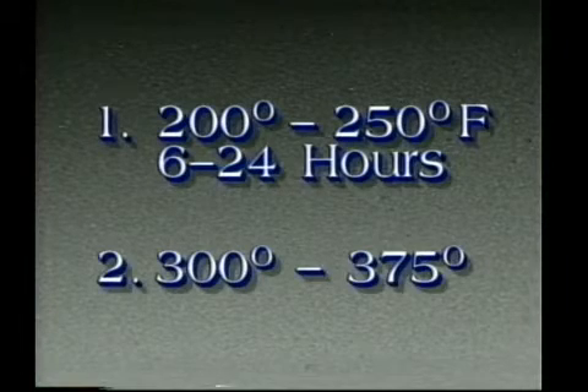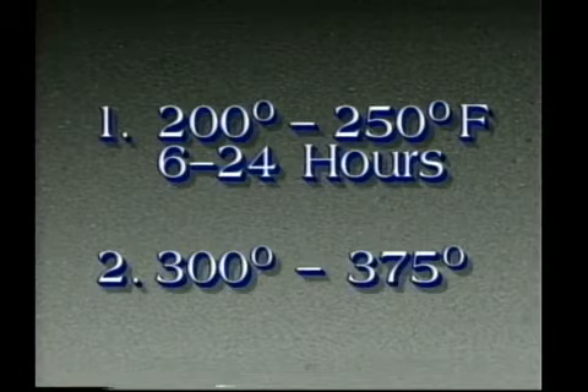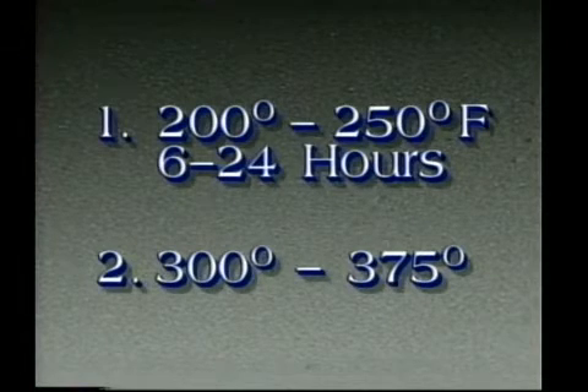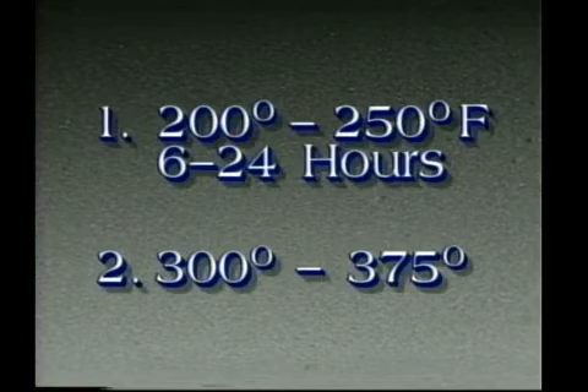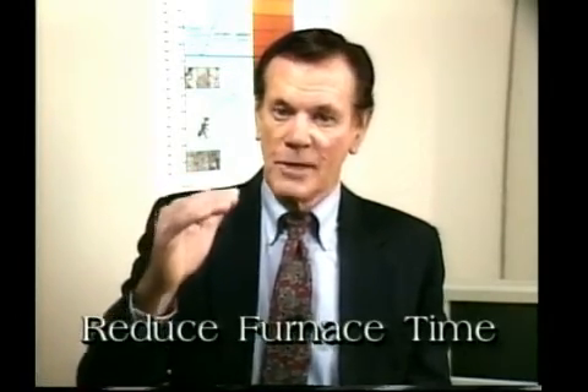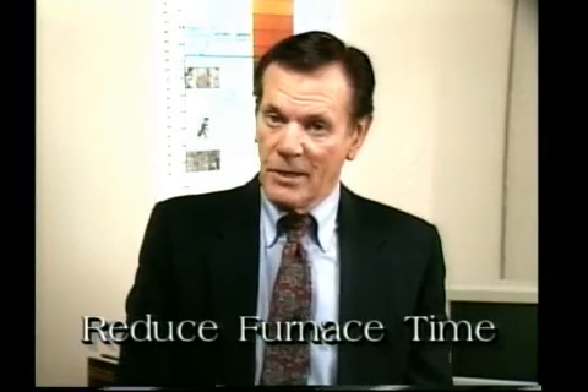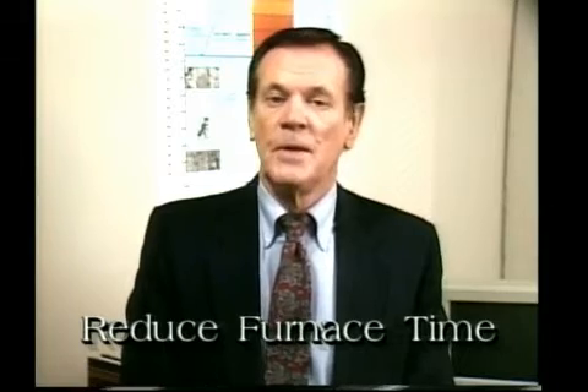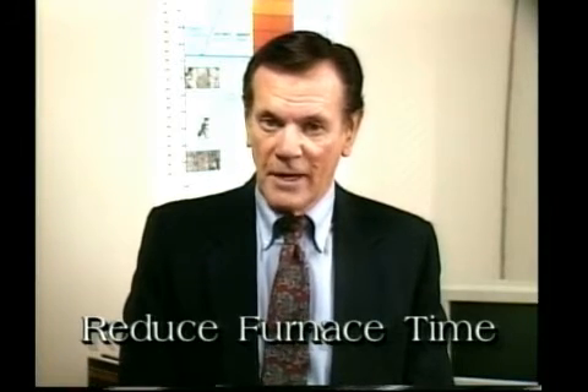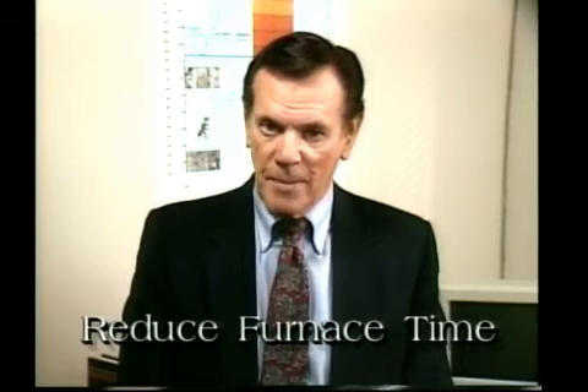In this procedure, the material is first aged at a lower temperature, such as 200 to 250 degrees for some period, usually anywhere from 6 to 24 hours. The alloy is then given a second and sometimes even a third age at a higher temperature, usually 300 to 375 degrees. The practice of two-step aging was first introduced in the 1950s in order to reduce the total furnace time required for some T6 aging practices, particularly those of the 7000 series alloys, which often required 24 to 48 hours of furnace time to obtain desired properties.